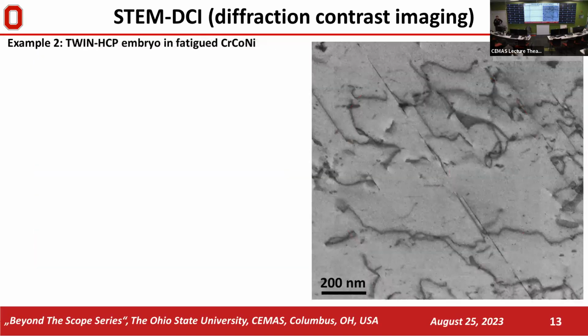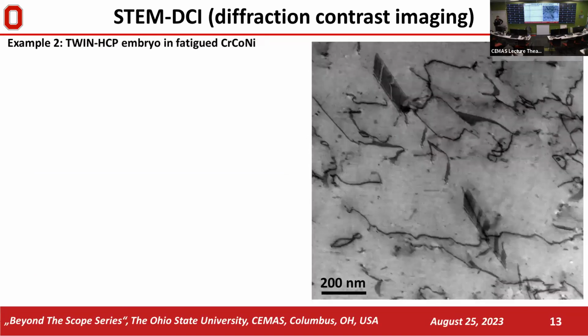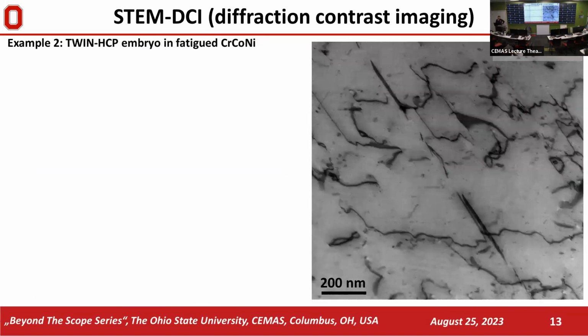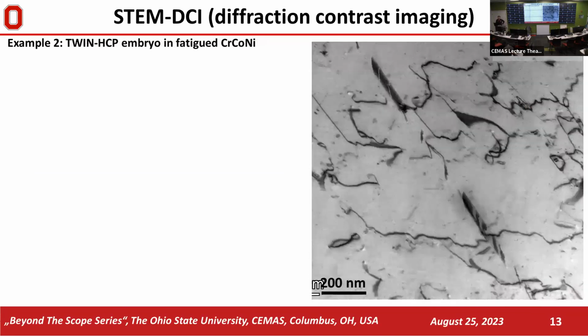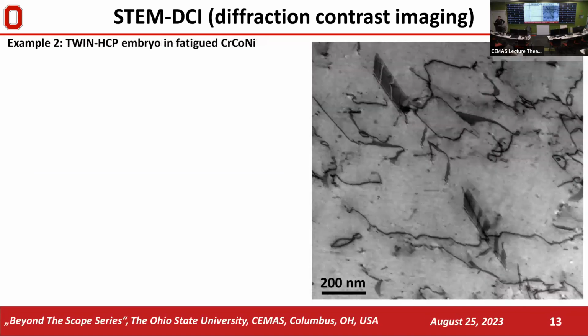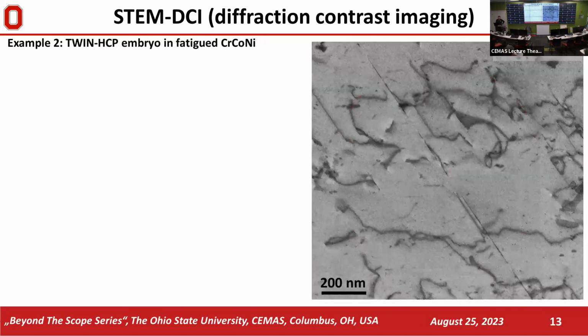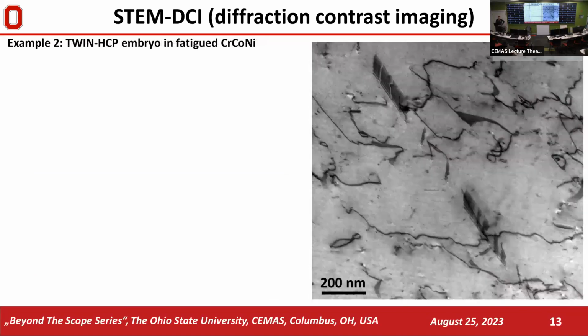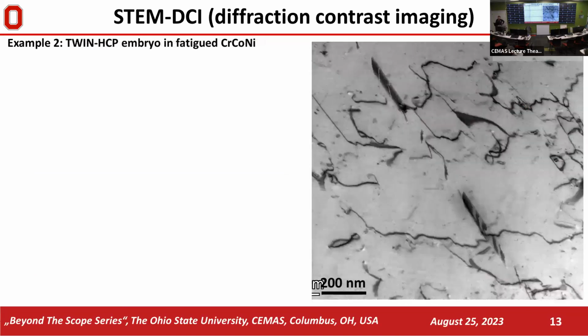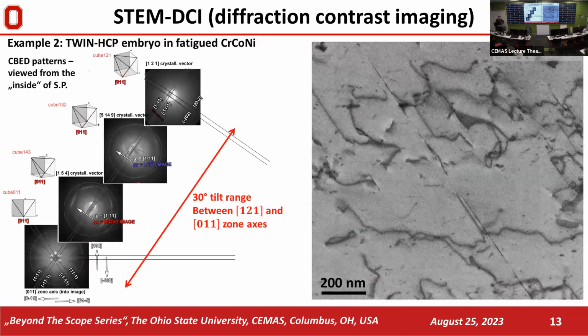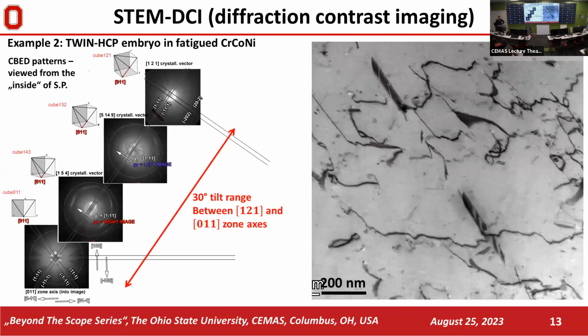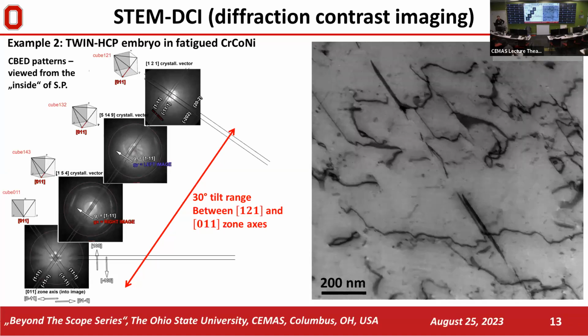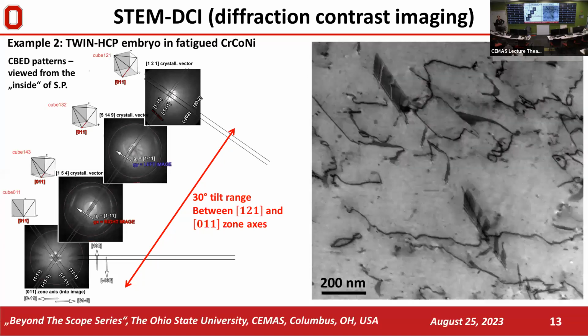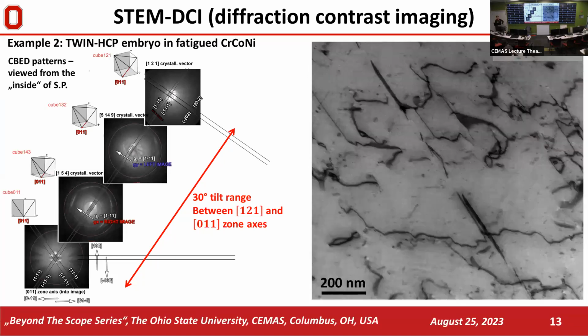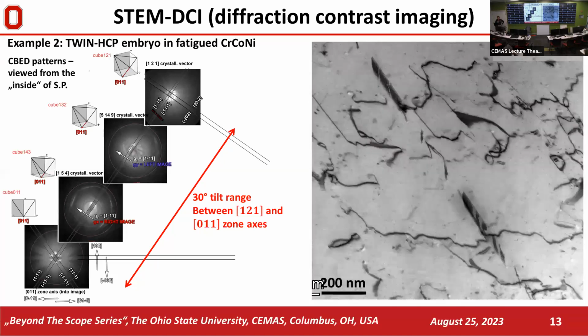And now let's talk about a different case. This is a twin HCP embryo, which is sitting in a slip band in a fatigued chrome cobalt nickel alloy, which is associated with GRX alloy. And let's talk about how we can use the STEM DCI to get different levels of information about such a structure, which then have implications for the study of mechanical properties of such alloy.